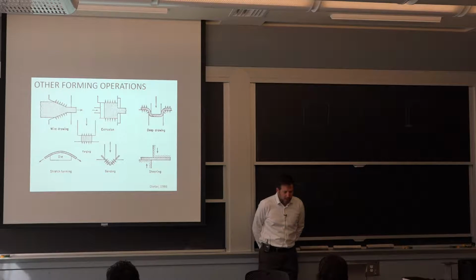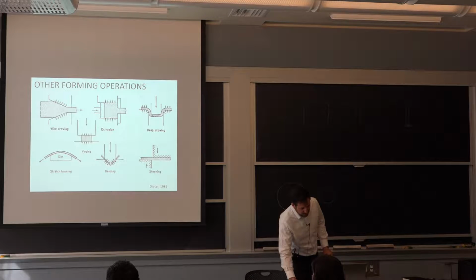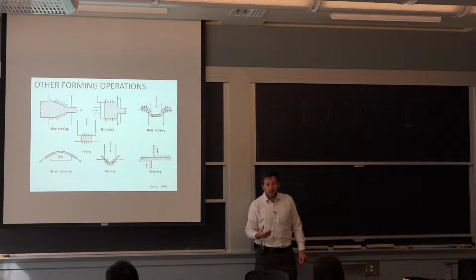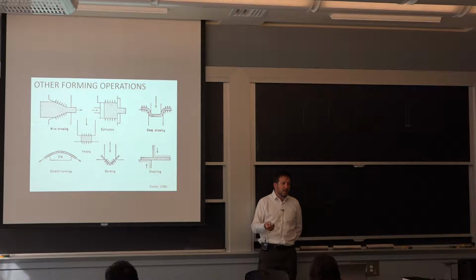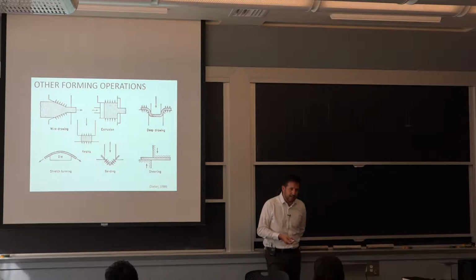What a deep drawing operation requires is a lot of strain hardening, because otherwise you start tearing in one area. It's a little bit like you have necking, like you have in a tensile test, if you don't have a lot of strain hardening. So there's specific aluminum alloy designed to be very, very soft to begin with, and then as they harden, they allow you to deform. Now, there are certain cans that are not done all at once, and that is because you want to stop and soften the material again, and then continue with the same hardening process.